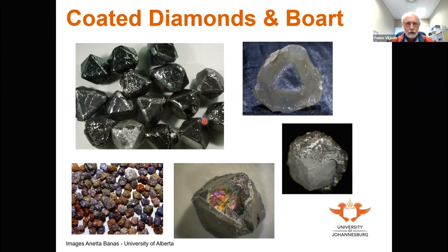When it comes to the more traditional coated diamonds, you can see some octahedra here with black coats on them. Some of the coated diamonds do actually contain a clear core, as you can see here, and that's then surrounded by this more cloudy growth zone of diamond. An example here of an octahedral stone with a coat that has been partially broken off. And here you can see a cubic stone that has some gray diamond coat on it.